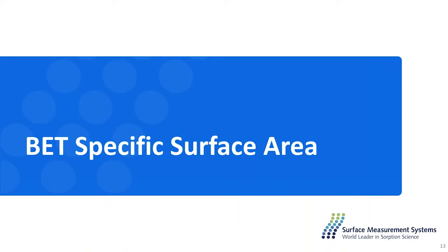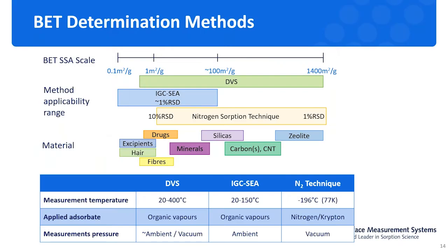So first, the major property measured by the IGC technique is the BET surface area. And here is summarized quite a different methodology for the BET determination, which is widely known in the volumetric techniques with nitrogen sorption. IGC is sitting in the range between 0.1 square meter per gram to 100 square meter per gram. And the major difference between the nitrogen sorption as well as the IGC technique is the condition that we